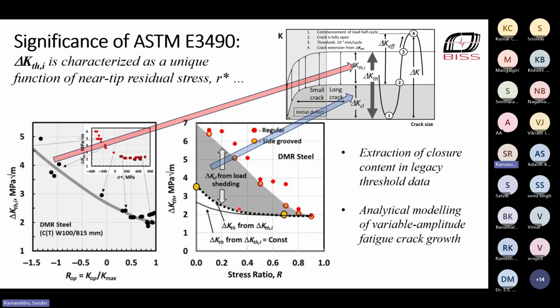So from these plots, you can see that the intrinsic threshold is not a constant. It's a property that is sensitive to near-tip residual stress. So as Vikram pointed out in the beginning, it is mean stress sensitive. And the second thing is, because we know how to determine it, we can also see how wrong we are in applying prevailing test methods to determine threshold.